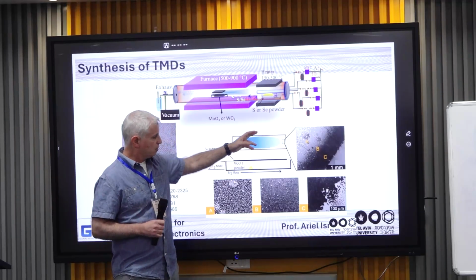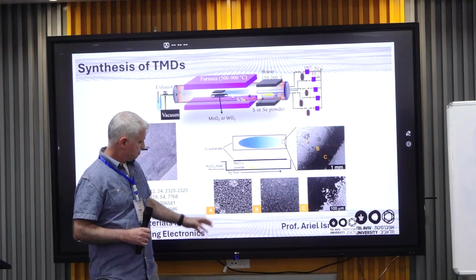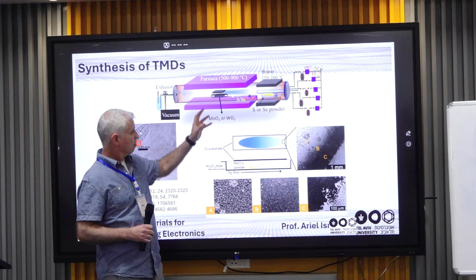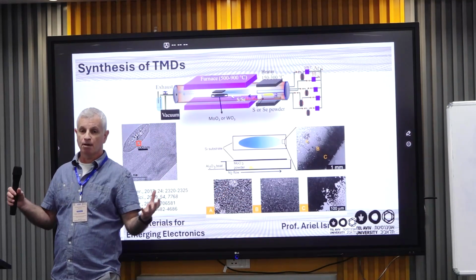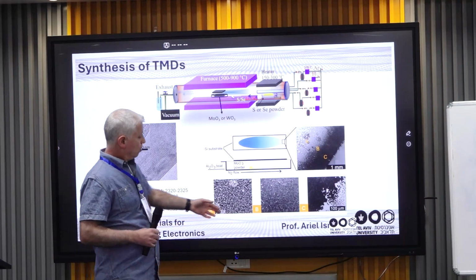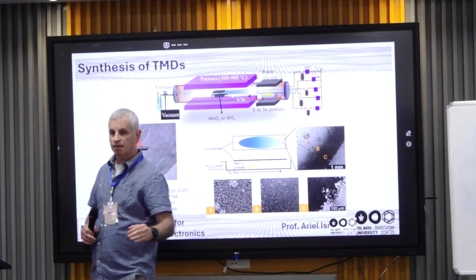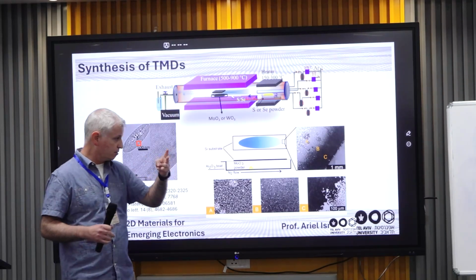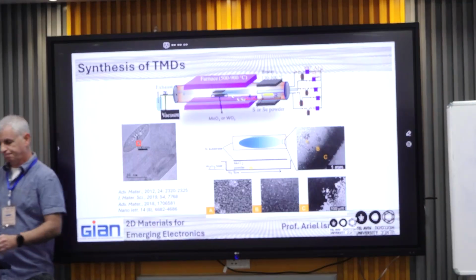The impact of the distance will be high because of the diffusion, right? So you will have areas with high flux of the metal, and therefore multi-layer structures, even standing flake structures. Then you will also have some areas with very thin layer formation, even atomic layers, in this case 3 atoms thick. But it is kind of non-controllable.